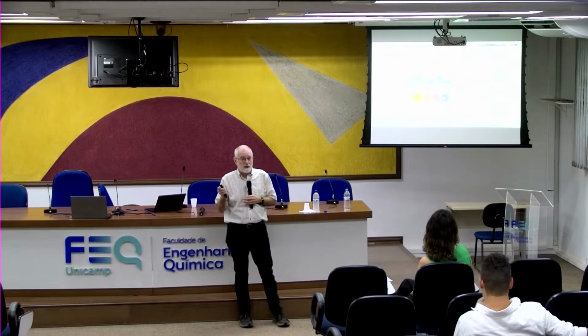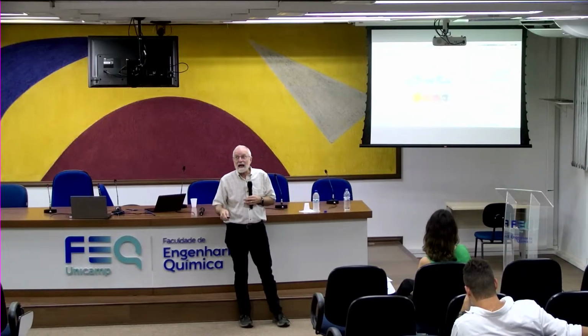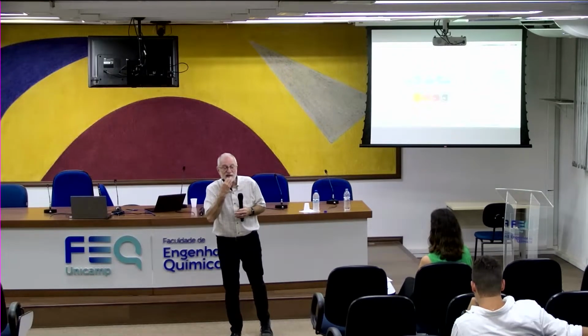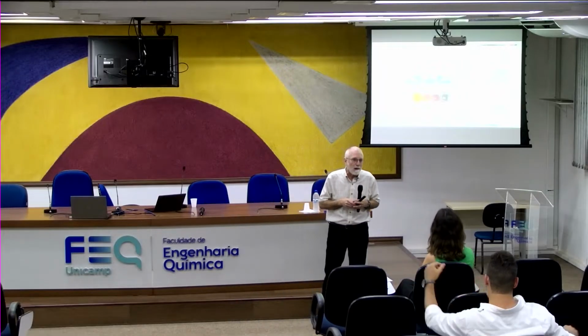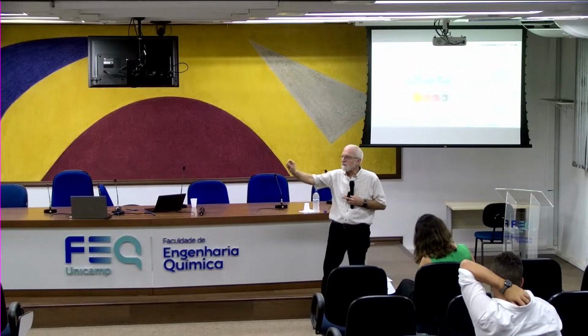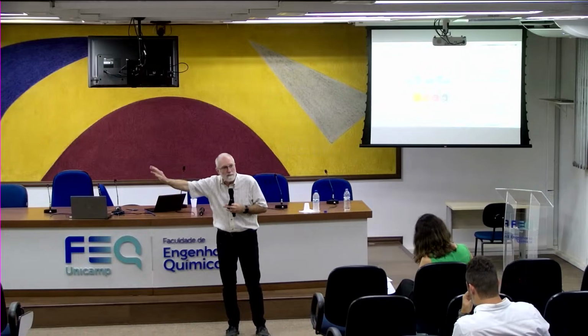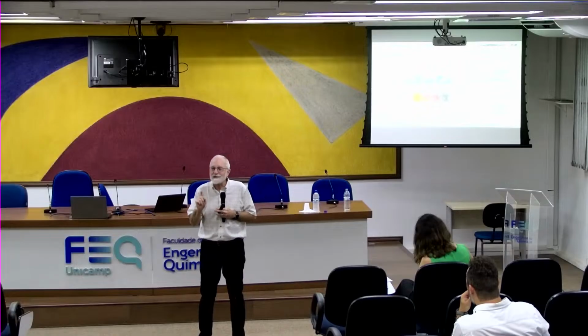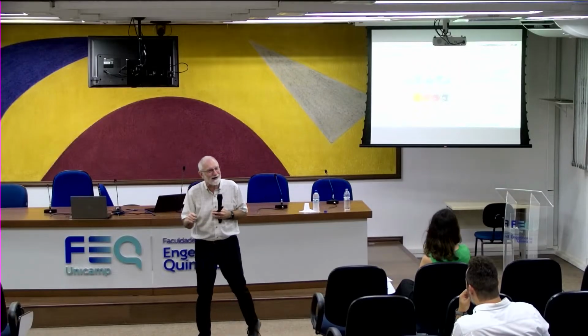Okay. So what we did was we took the same material. It's just got a little bit of sugar. And unsurprisingly, the longer you heat it, the more caramelization takes place, and the more caramelization, the more viscous the material. If you think about this, where would this be useful? Where you have to do a small seal or fix something, and you put in this fluid that you can inject where you need it, and then heat it up till it's cured? No, till it's the right color, because you know it's also cured. So you don't need a high technical degree of skill to make this work.